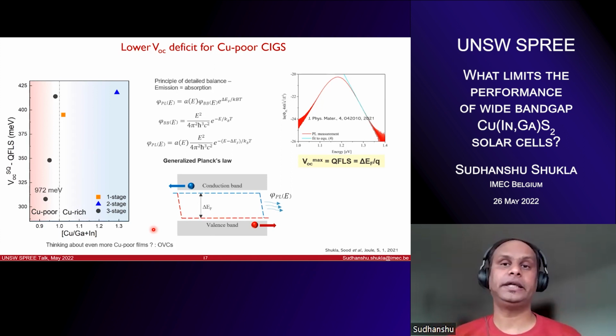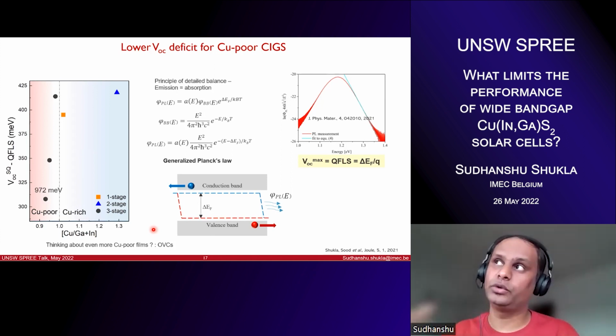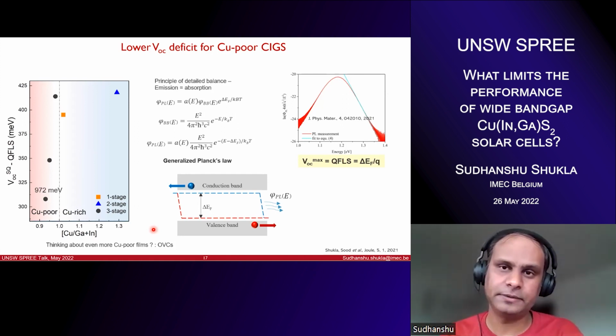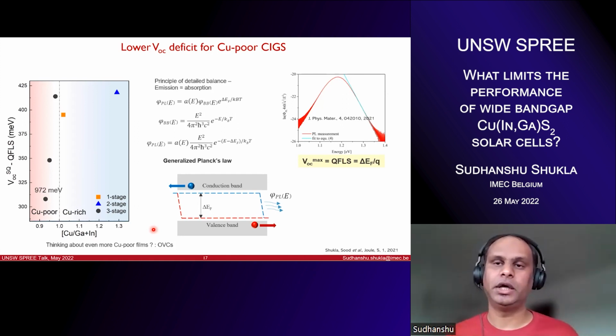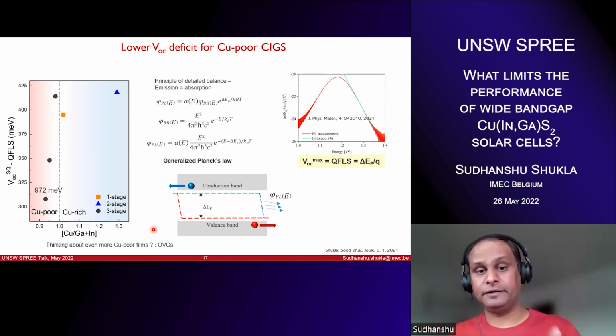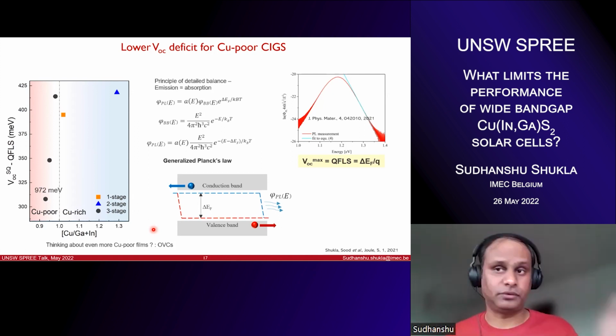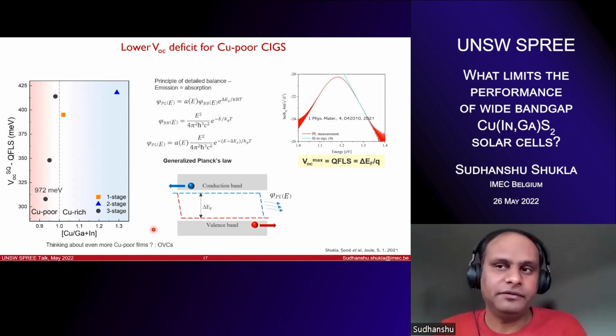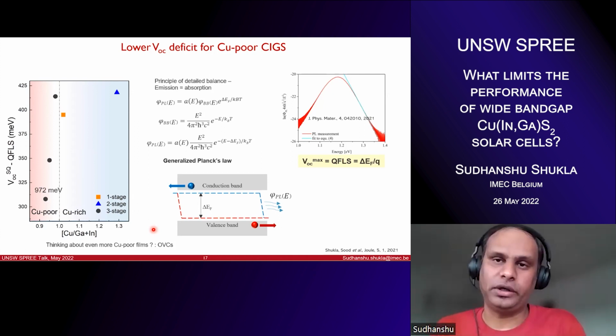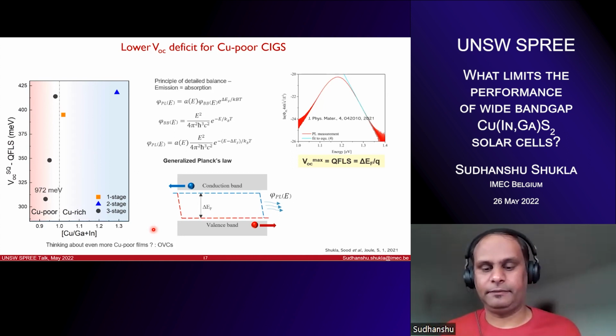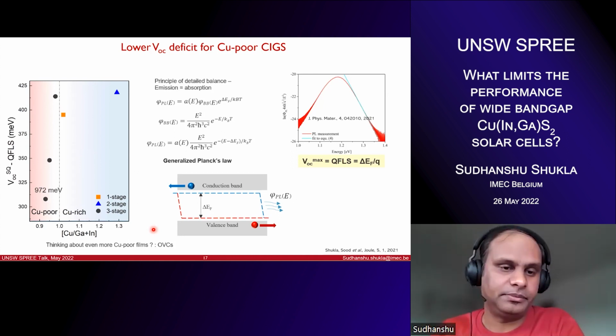Because selenides and sulfides are not equivalent when you look at their thermodynamic stability range, they are not the same. For example, when you want to make copper indium 5 sulfur 8 or 1-3-5 or 1-5-8 compounds, 1-3-5 actually doesn't form at all in the case of CIS. And for that, you can look at some papers on the thermodynamic phase diagrams of CIS, CIGS from Alain Lafond.